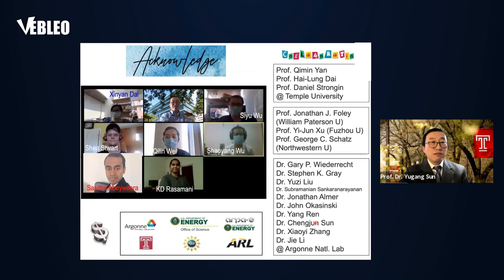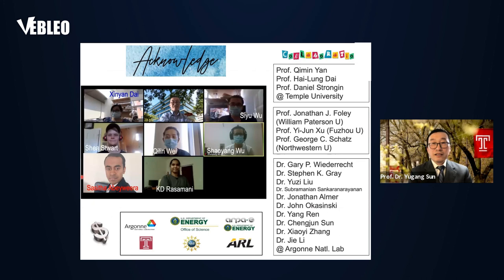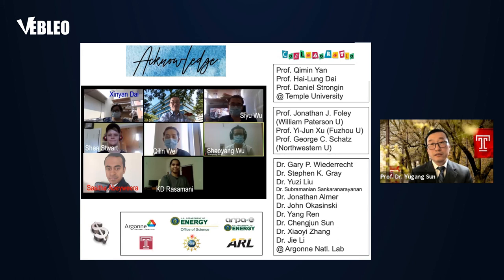In summary, we use glass beads as a light antenna to enhance optical absorption power in quantum-size metal nanoparticle catalysts. These quantum-size metal nanoparticles under photo illumination can efficiently generate and inject hot electrons into surface adsorbates compared to larger metal nanoparticle catalysts. Using this composite catalyst, we can enhance reaction kinetics and selectivity for different types of reactions including oxidation, reduction, solution-phase, and gas-phase reactions. Finally, I would like to thank my students for working hard during this tough time, and I appreciate the financial support from various agencies and the collaborations. Thank you.